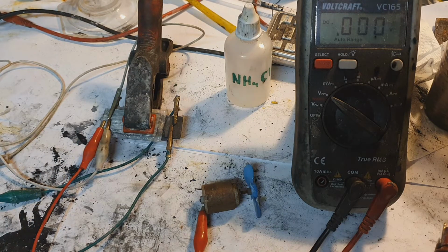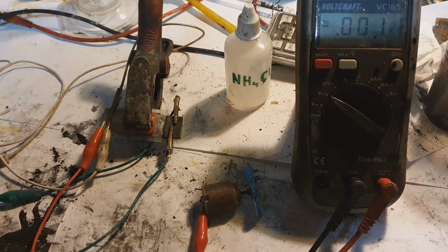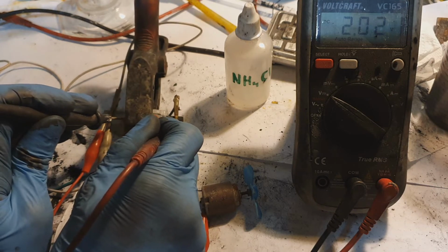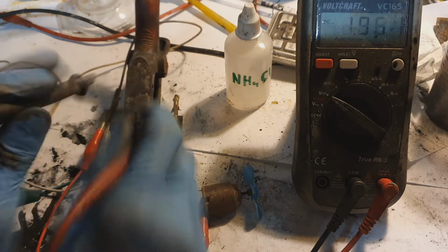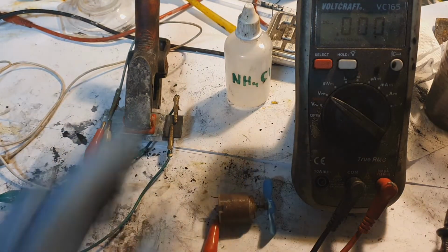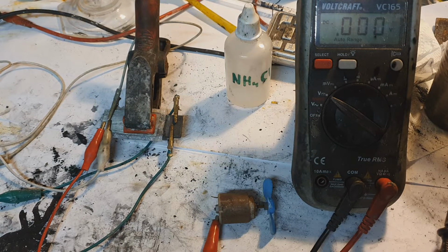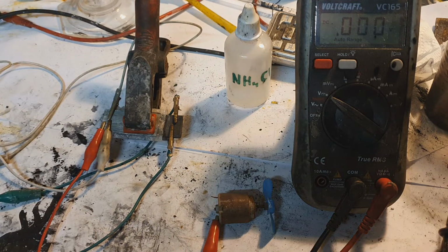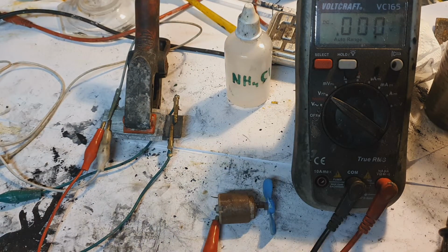So right now this one is quite fully charged. I will disconnect my power supply and I will show you the voltage. Two volts. Really nice. So in the patent I see that some tin zinc battery you need to charge with 4.5 volts to get 2 volts of cell voltage. I charge this cell with 2.2 volts because charging voltage of 4.5 volts is a little bit high, but I'm really happy that I can get a cell voltage of 2 volts with charging voltage of 2.2 volts.